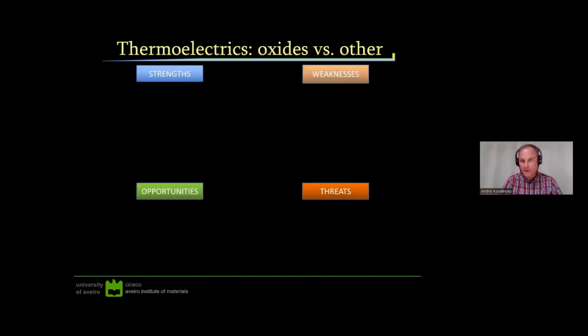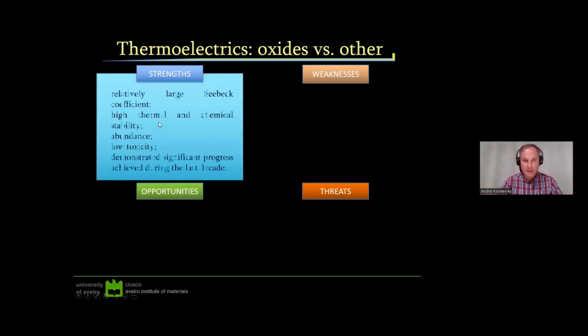Let's do a kind of very simple SWOT analysis of oxide materials in general. The strengths: they normally have a large Seebeck coefficient, they're pretty stable, they are abundant in most cases, and they don't have high toxicity. And again, as I said, there was demonstrated significant progress achieved during the last decade for these materials.